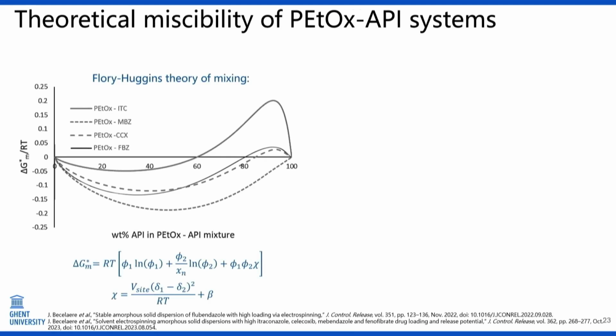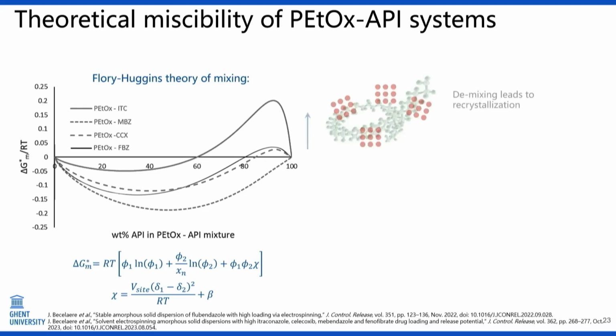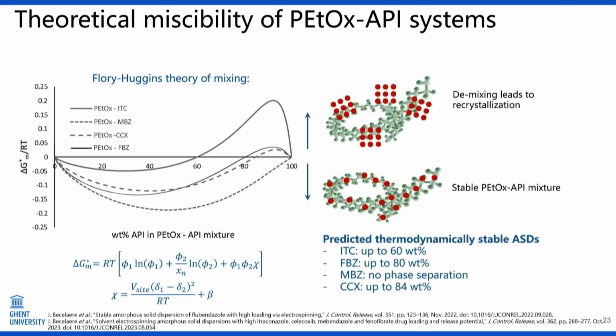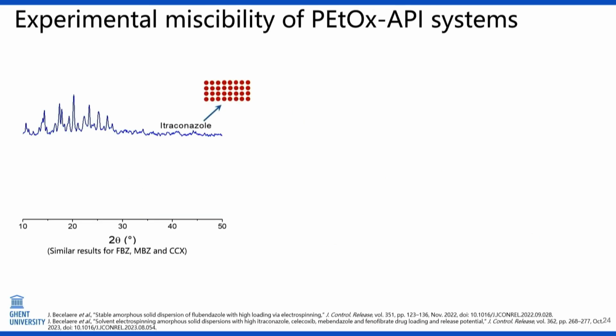And then this was also underpinned by theoretical studies such as the Flory-Huggins theory of mixing. If you do the theory, it predicts that as long as you can keep it in the amorphous state during processing, you should be able to have a good mixing up to, depending on the drug, 60–80%. And we want a good mixing. If we don't have a full mixture, then demixing over time will lead to crystallization and a non-stable dispersion. So, is it indeed true?